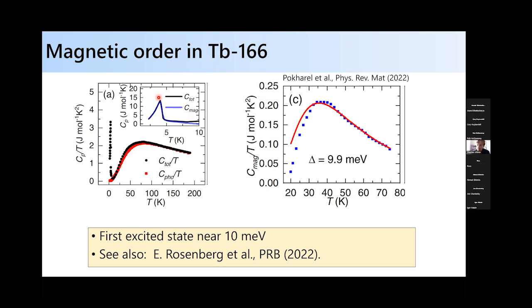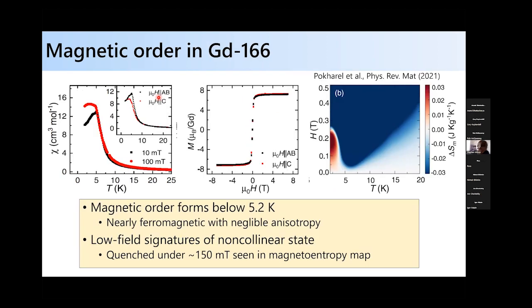Okay, so then we can look at the opposite extreme, and we can replace terbium with gadolinium. When you do that, we should be looking at a much more isotropic ion, the gadolinium 3+. If you look at the susceptibility as a function of temperature as you cool down, in the low field limit under 10 millitesla, you can see there's a downturn and maybe some subtle structure in the susceptibility as you field cool the system. If you were to apply magnetization in the ordered state, either with the field orthogonal to the Kagome planes or within the Kagome planes, you can see that the response is pretty isotropic, as you would expect.